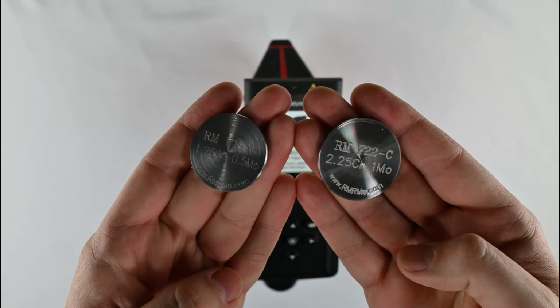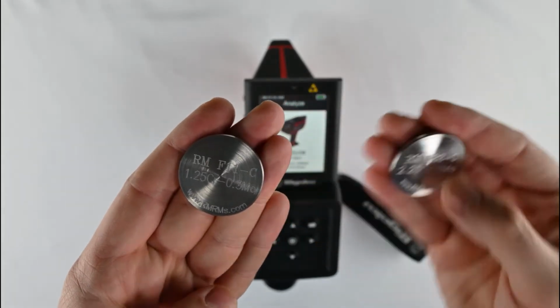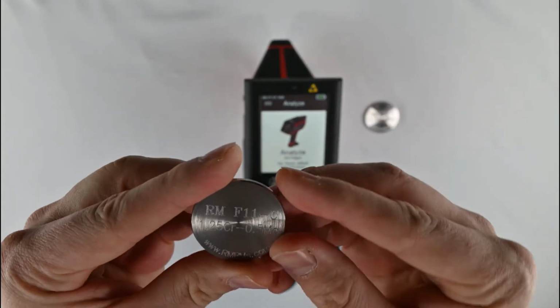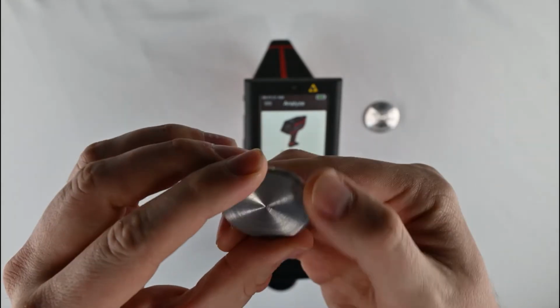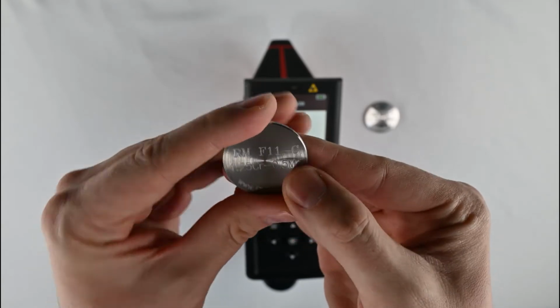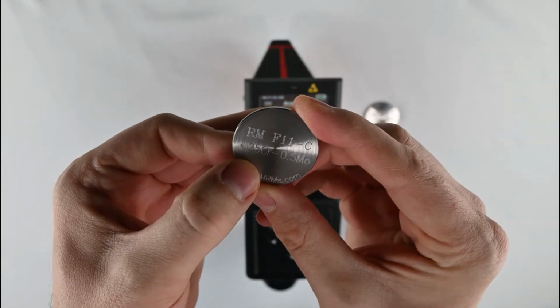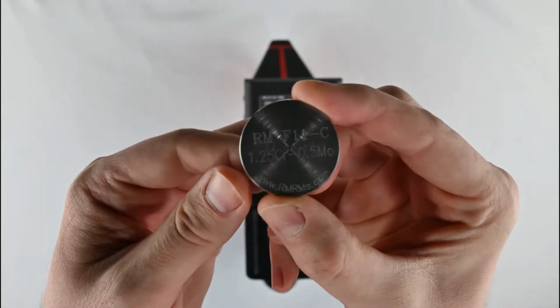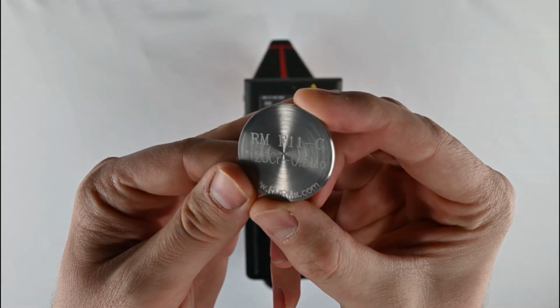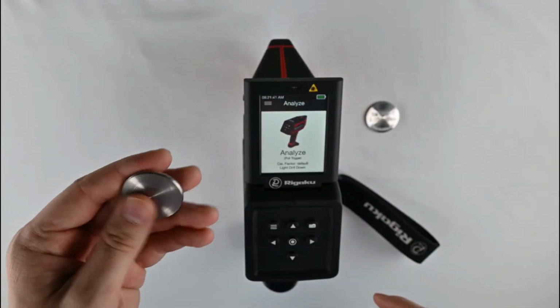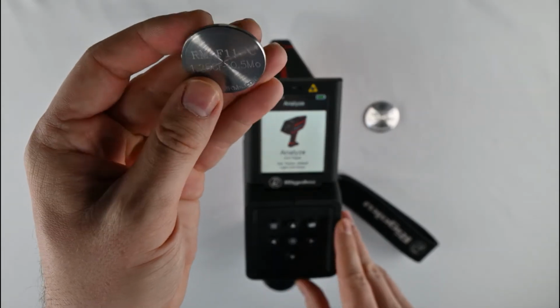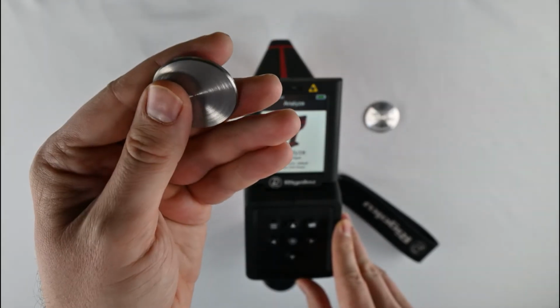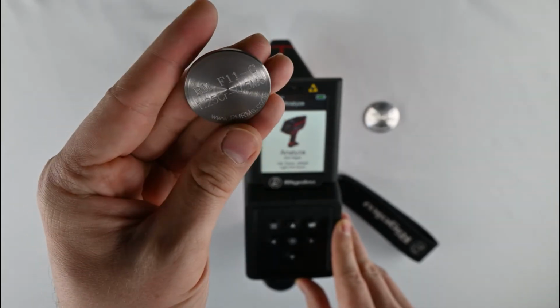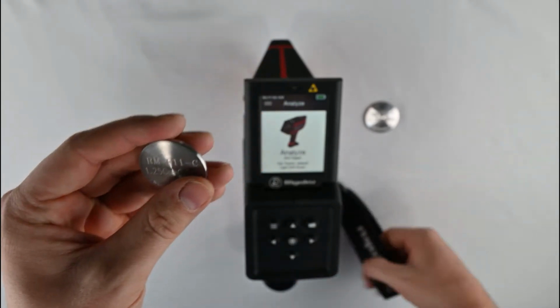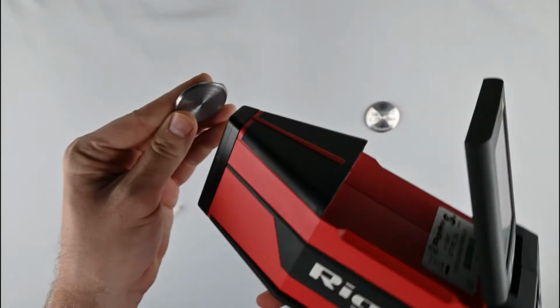Okay, so first up here, we've got F11. We'll do F22 in a moment. Now, F11 is typically called F11 Class 2. The cast grade for this is WC6. It's also typically referred to as 1 1/4 chrome and half moly, so you can see that's written right on this sample. It can be used up to 593 degrees Celsius or 1100 degrees Fahrenheit, and has a tensile strength of about 70 KSI. So let's take a closer look and see what this looks like.